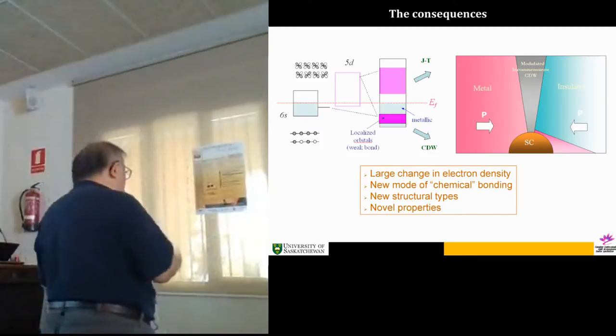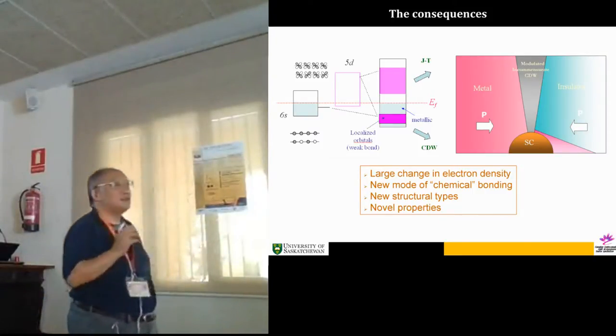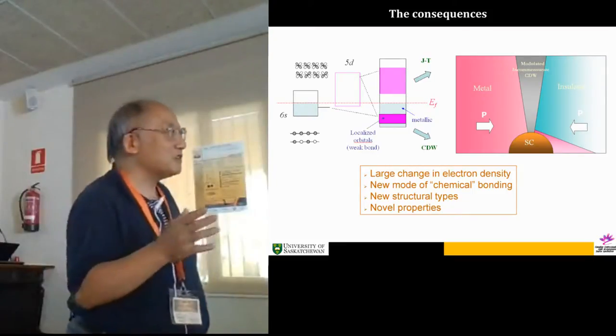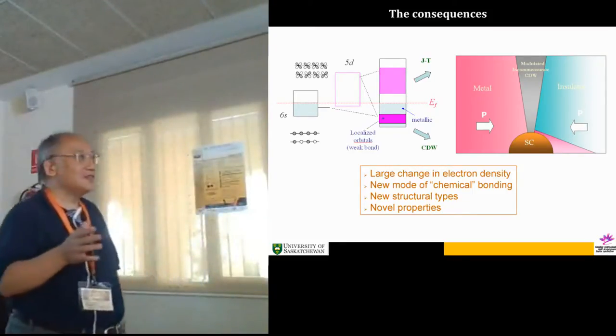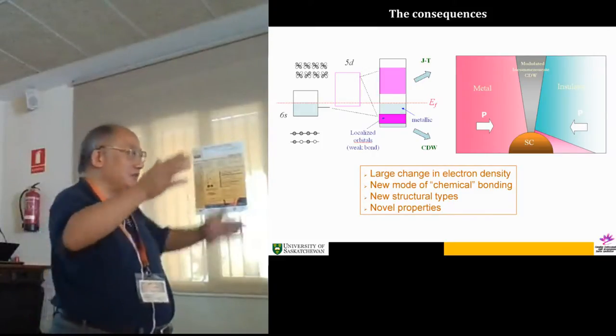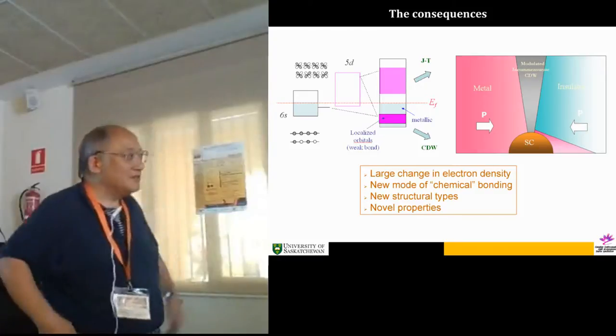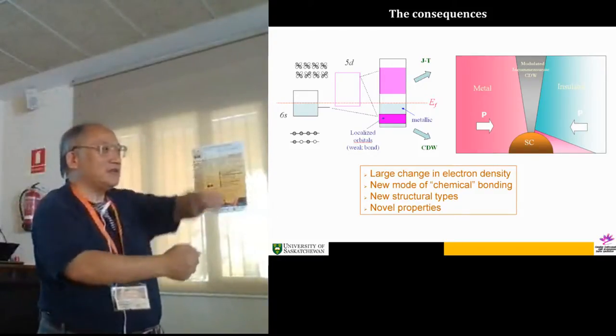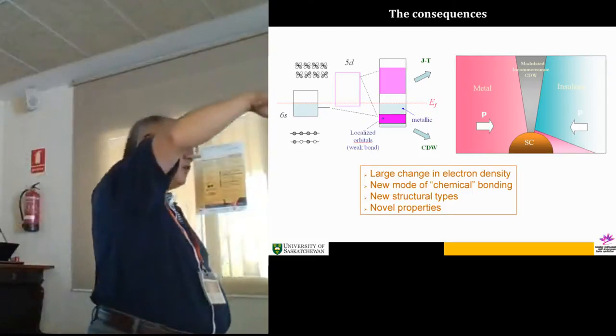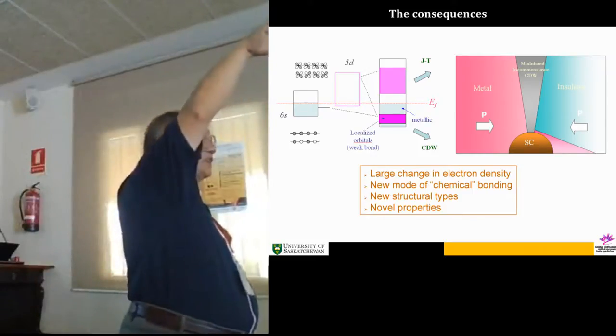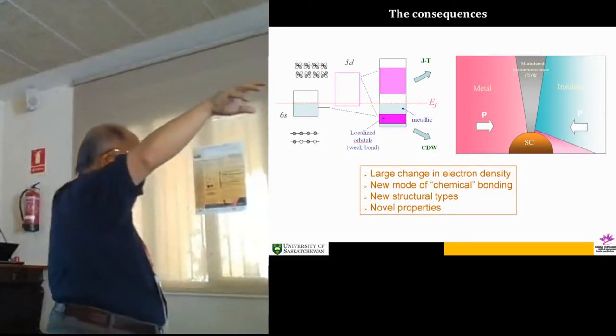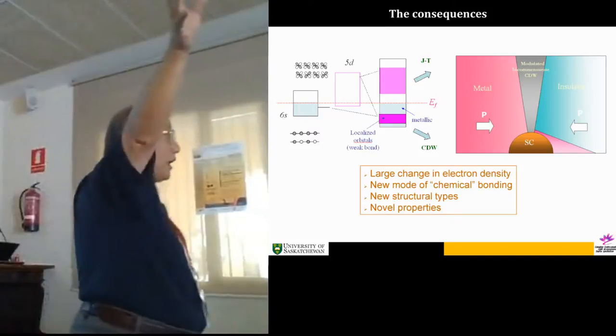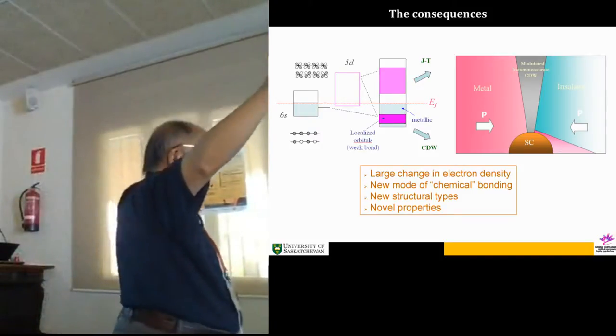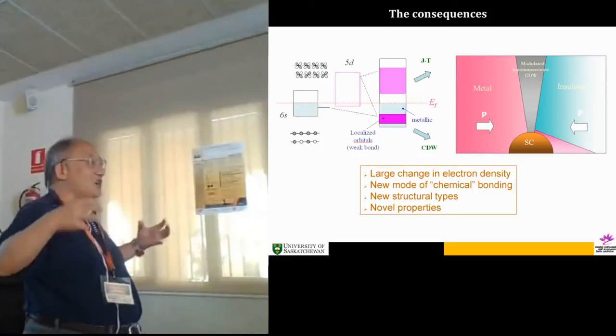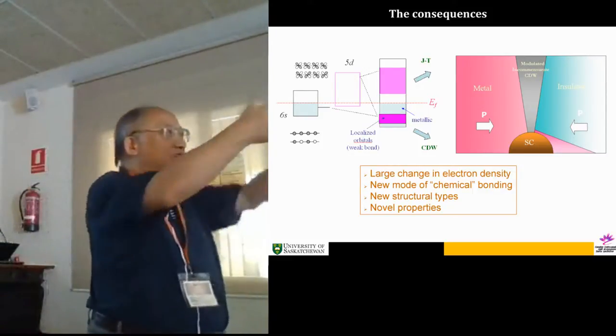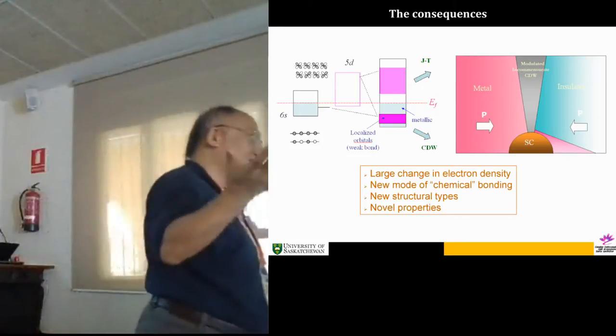Now think about it, it's very simple actually. It's a particle in a box, and I think everybody here probably has had training on a particle in a box. That's the first thing you do before you solve the Schrödinger equation, all right? So the energy is inversely proportional to the square of the dimension of the box. You compress the atoms, what happens? The electron levels go up. Basically, the highest occupied orbital becomes higher and higher in energy. Now, for alkali metals, the ionization energy is already low. So you compress it, it just goes away. So it goes away, where to go? So we see the positive charges form the lattice, and they condense, they pair up to form this so-called electride.